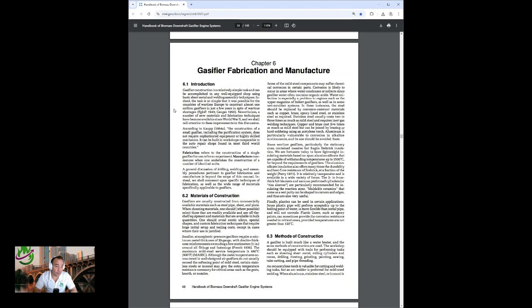Corrosion is likely to occur in areas where the water condenses or collects, since gasifier water often contains organic acids. Water collection is especially a problem in regions such as the upper magazine of Imbert gasifiers, as well as in some wet scrubber systems. In these instances, the steel should be replaced by corrosion-resistant materials such as copper, brass, epoxy, or lined steel, or stainless steel as required.